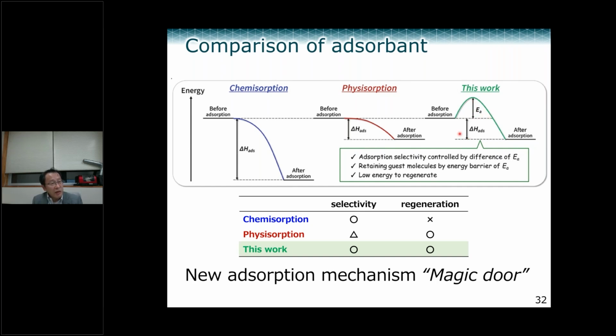Only this energy is needed, because when you absorb CO2, heat is generated. You can use that heat for regeneration, so eventually you can cancel out this energy. In our material, you need only this energy for regeneration. That's why we summarize it in this table. In the chemisorption case, selectivity is quite nice, however for regeneration you need a relatively big energy. In the physisorption case, in general, selectivity is poor but regeneration is easy. But our material satisfies both conditions. That's why we named this the magic door system.